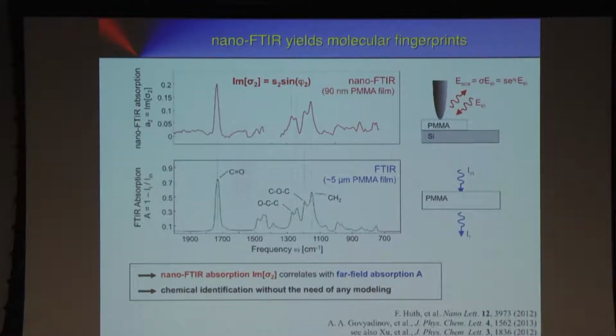Yeah, so this we can see here. So the first experiment we did is we placed the tip on a simple PMMA layer, and we record a spectrum. And we get an amplitude and a phase spectrum, but what we plot here is the imaginary part, right? So we see here these lines that resemble an infrared spectrum. Then we took a few micrometer thick PMMA, made a transmission Fourier transform experiment, and we record the spectrum. And now we can compare directly, and we see that the peak positions, the peak heights even, they match very nicely.